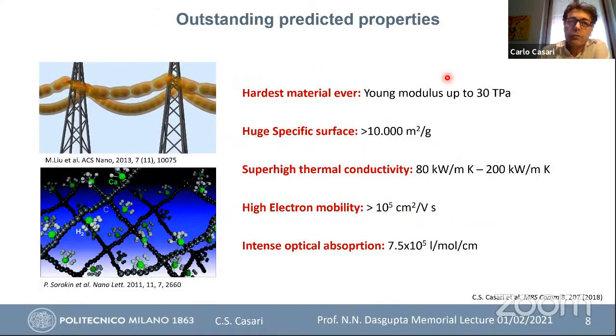Okay, so of course, based on this, these kinds of systems were very appealing for theoreticians, and so based on theoretical predictions, you can see that the predicted properties could be very, very appealing and interesting. For example, an extremely large Young's modulus has been predicted, up to 30 terapascal, that makes this material the hardest material ever. Also a huge specific surface, predicted to be larger than 10,000 square meters per gram. That is 3 times the one of graphene, or something like that.